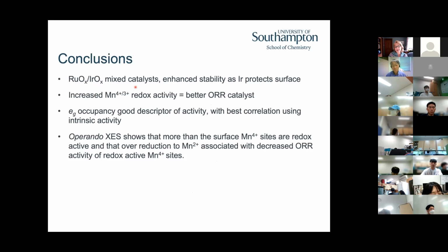But for the ruthenium-iridium mixed catalyst, we think this enhanced stability is because the iridium protects the surface, but also that the activity of that iridium at the surface is enhanced by the ruthenium being subsurface. For the manganates, it's the access of this manganese 3+/4+ redox activity that gives you the best catalyst, and you want to avoid over-reducing to form manganese 2+. So that eg occupancy is still a good descriptor of the activity of the material. And I encourage people to start exploring these new techniques using X-ray emission spectra. It allowed us to gain more information than the single parameter we could fit with just the XANES.